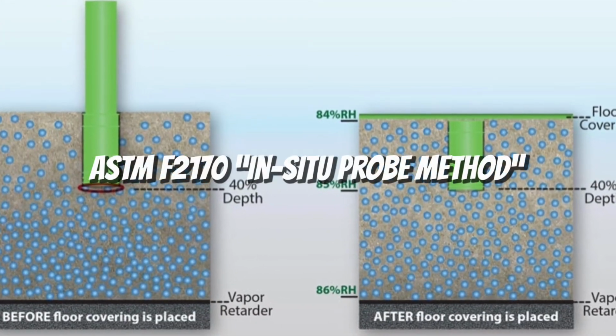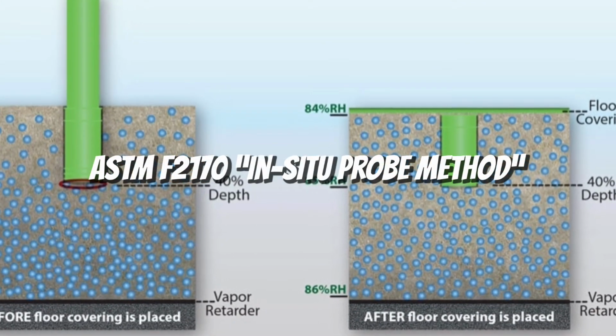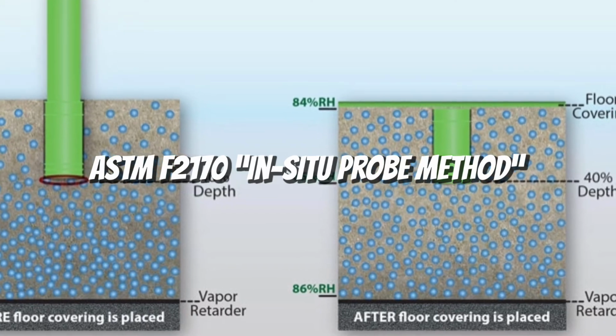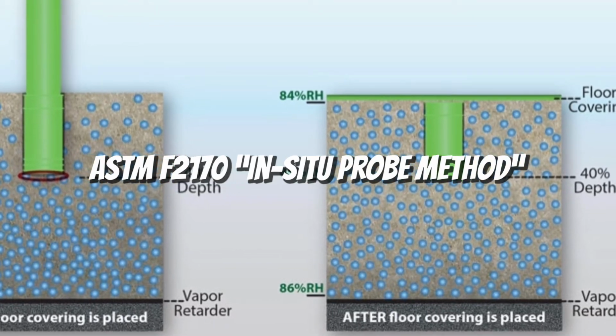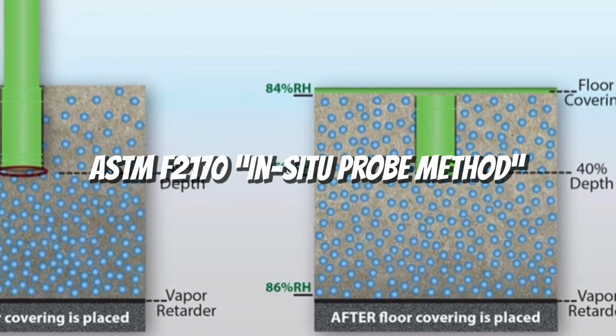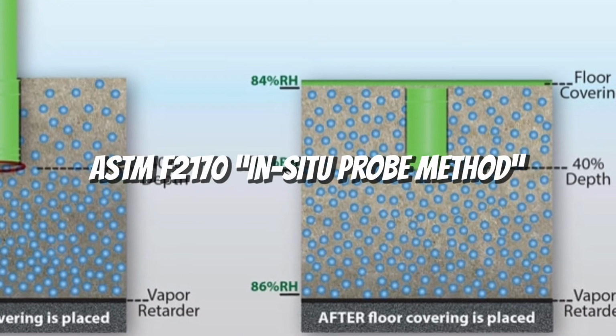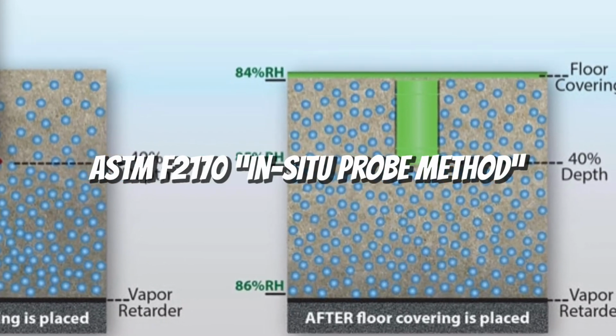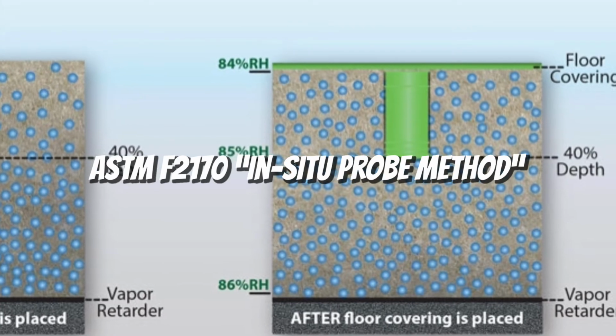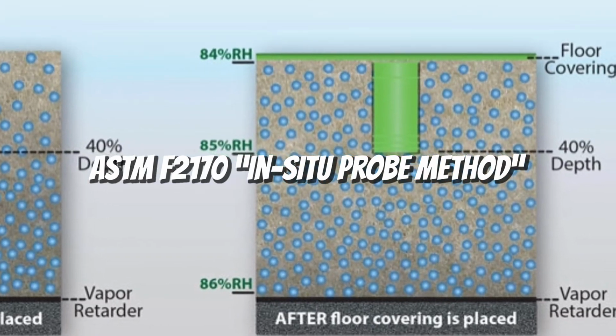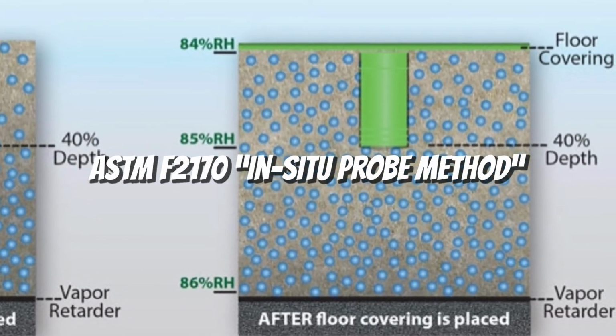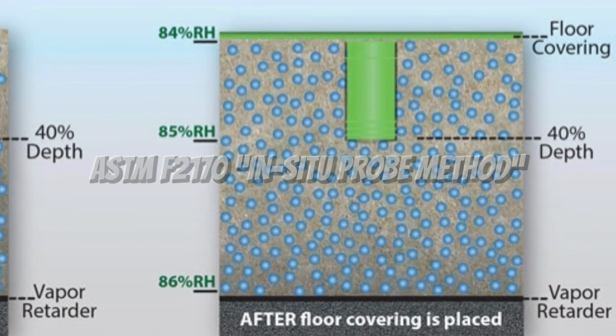ASTM F2170, determining relative humidity in concrete floor slabs using in-situ probes. In this test, a sleeve or a probe is inserted into holes drilled into the concrete. The test is more precise because it can show humidity readings at various depths in concrete. Probes can also be left in the concrete to deliver readings over time.